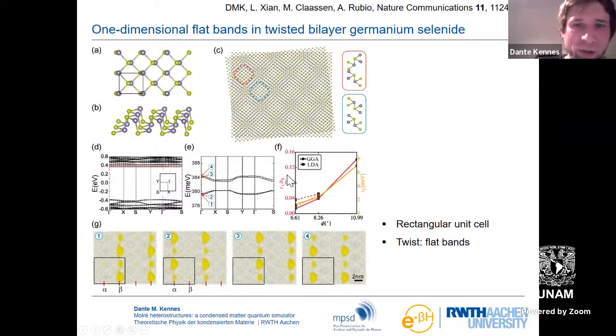But then there's also the ratio of the quantity that we call T perpendicular divided by T parallel. That's how one-dimensional my system is. So the smaller this number is, the more one-dimensional it is. So it's measuring kinetic energy out of the chains versus within the chains. And as you see, as you go to smaller twist angles, the red line, this left axis here, decreases quickly, meaning that you establish more and more the one-dimensional limit.